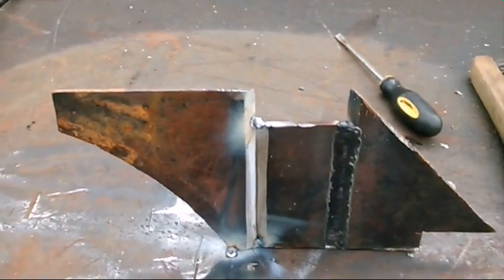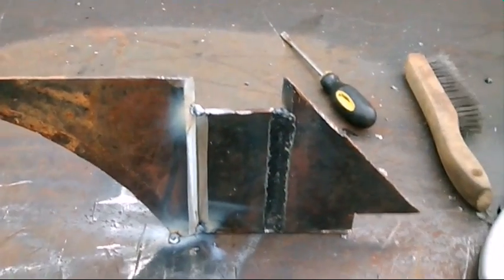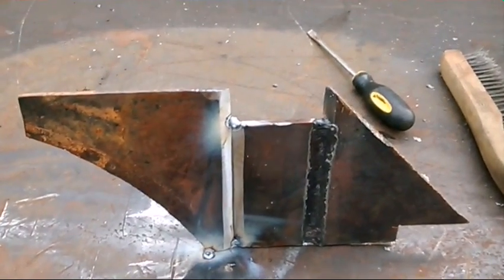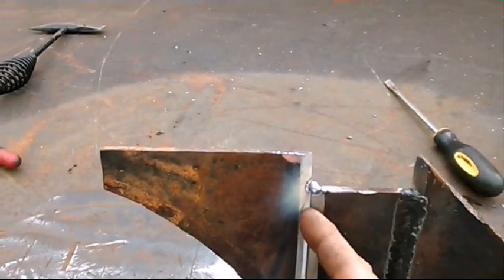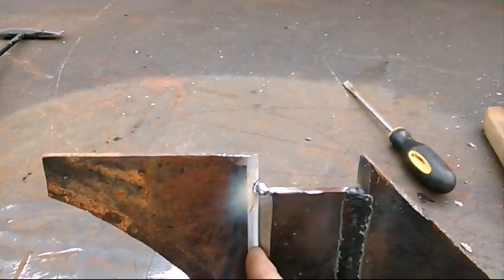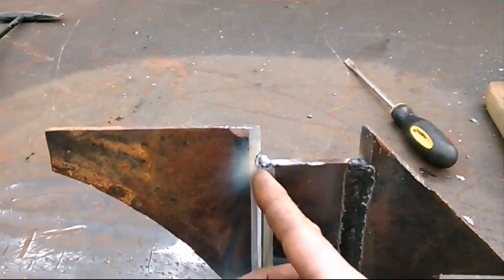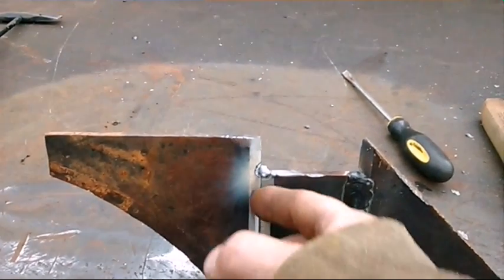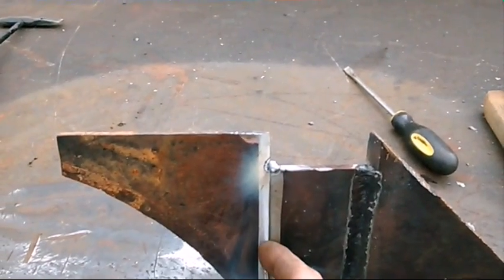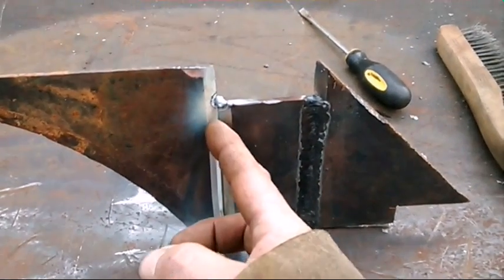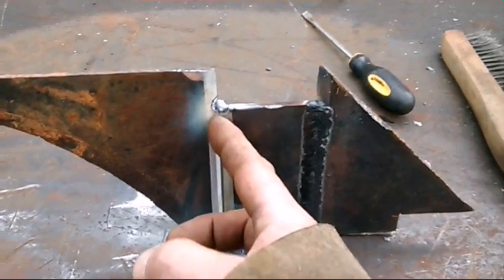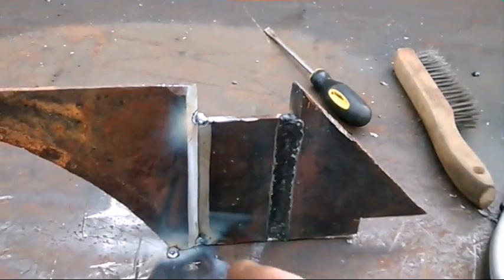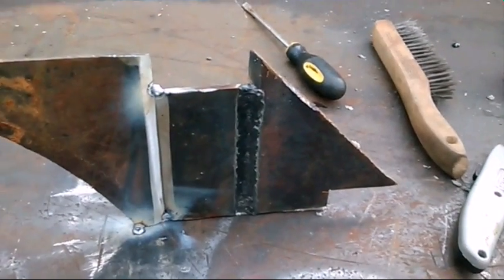All right, I cooled the plate off. And I got it set in an upright position to where you would go uphill if you wanted to go uphill or if you needed to go uphill. The first thing I would do, since it's beveled down pretty thin right there, I would turn the settings down and drag a root downhill in the center right there. Because if you just try to go up without a root in there, it's going to want to blow out a whole lot. So I would turn the settings down to probably the eighth inch settings and just drag a root down, clean that up, let it cool off, and then come back and go uphill.